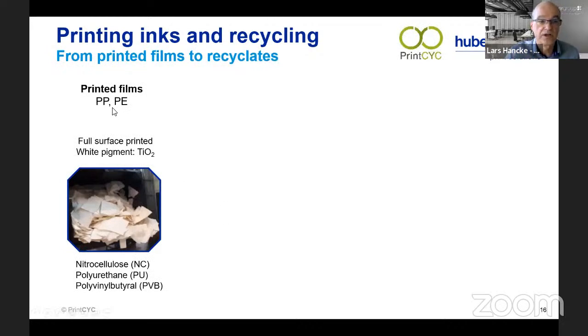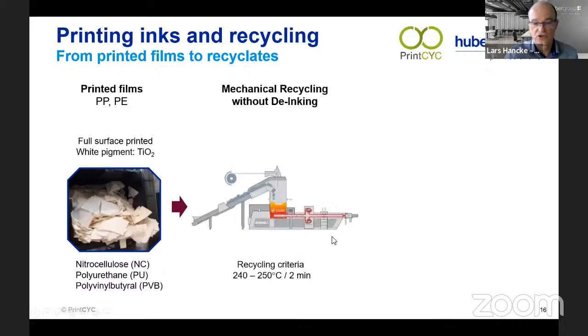So we started with polyethylene and polypropylene printed only with white, because the titanium dioxide pigment in the white is stable. It is even stable at 1,000 degrees Celsius. So the recycling process is not a challenge for the pigment. And we checked the three major binders that we thought are interesting for our industry. Of course, the nitrocellulose, because it accounts for the majority of the printing inks that we find in Europe for flexible film printing, the polyurethane inks, and also polyvinyl butyral PVB inks, because these two are more heat resistant than the nitrocellulose. And then we put it into an EREMA recycling machine, where basically the printed film is shredded, melted, and then extruded to form some kind of spaghetti, and the spaghetti is sliced into a granulate, and the granulate can then be used to produce new plastic materials, new plastic films, or other plastic materials.